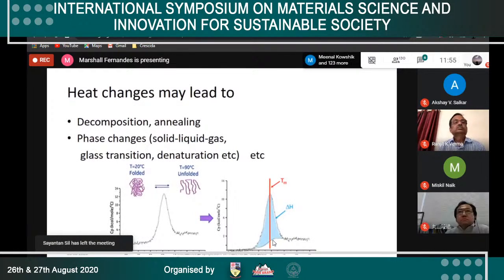And then just see, this is the specific heat. The specific heat versus temperature curve will come like this. So from differential scanning calorimetry, we can find out the specific heat, Cp. Cp comes from the same instrument, against temperature. So this peak, and the peak analysis is very important. What is the maximum temperature, Tm, and the area under the curve indicates the enthalpy change.